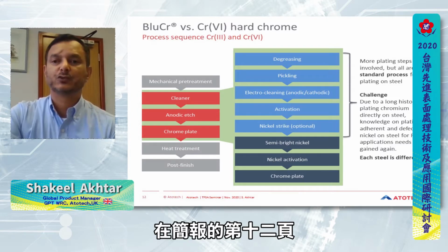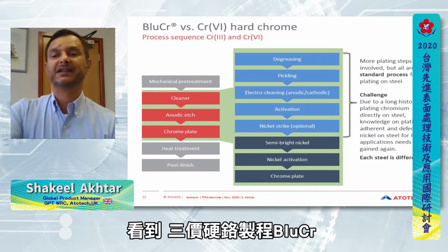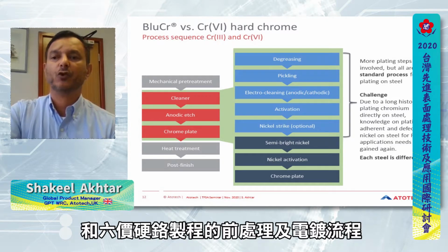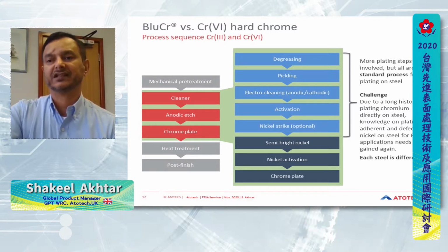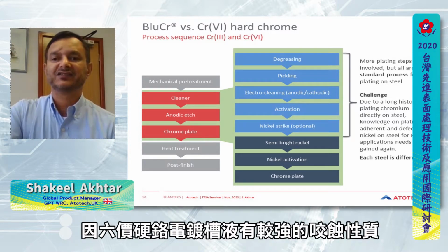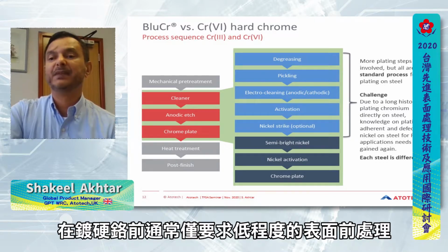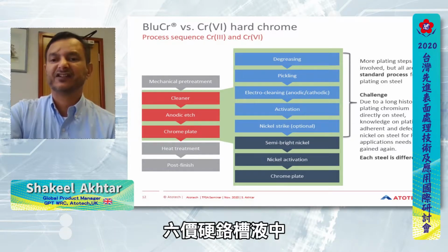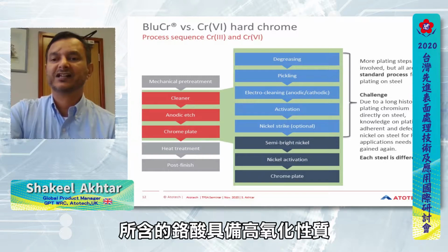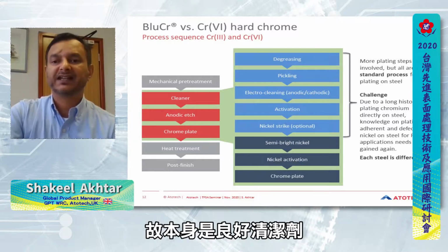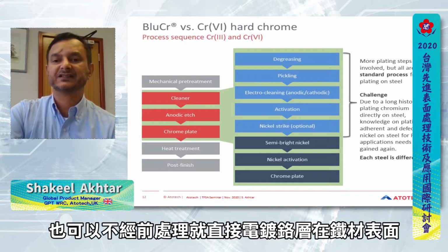In slide 12, we can see the pretreatment and plating sequence for both the processes. Due to the aggressive nature of the hexavalent process, it requires a bare minimum of surface treatment prior to the chrome plating. The hexavalent bath is a good cleaner due to the highly oxidizing nature of the chromic acid. It also plates direct onto the steel surface.